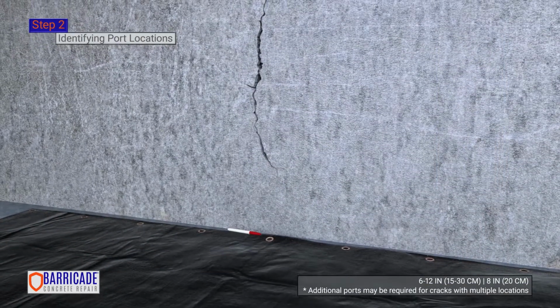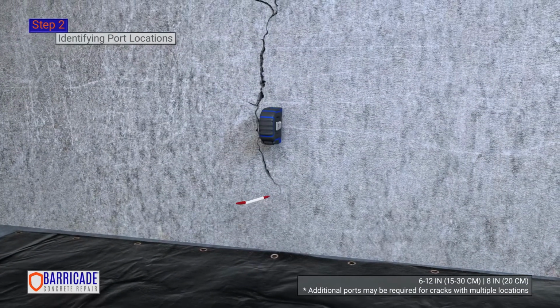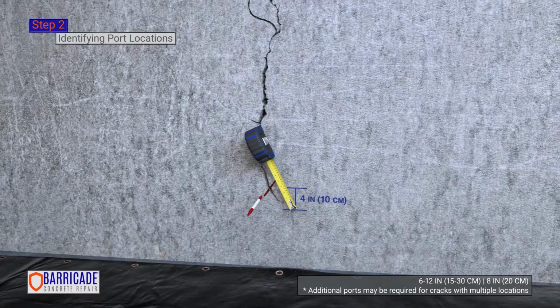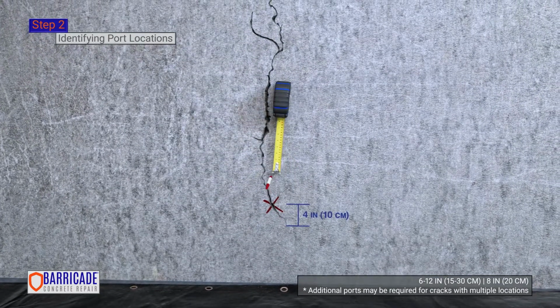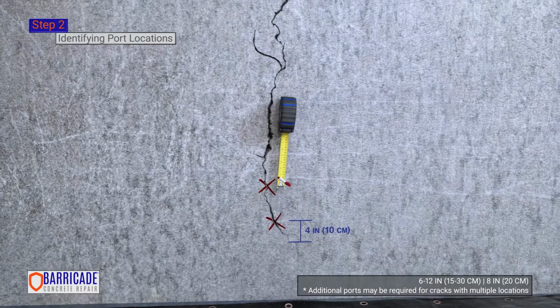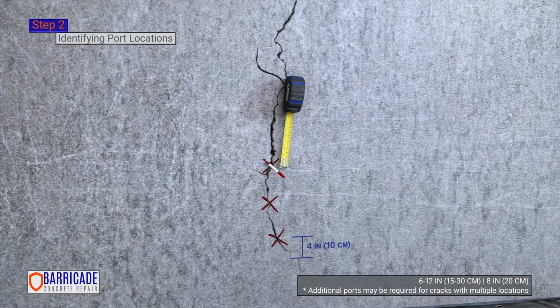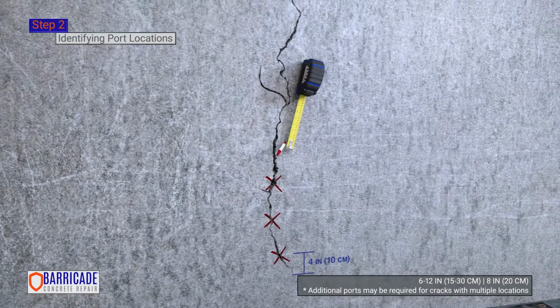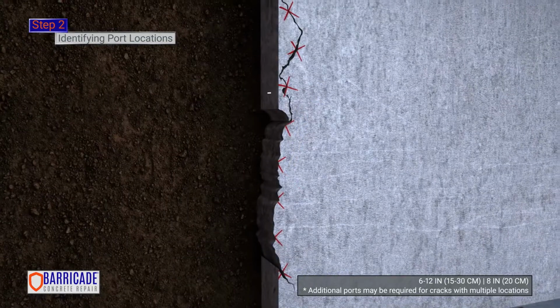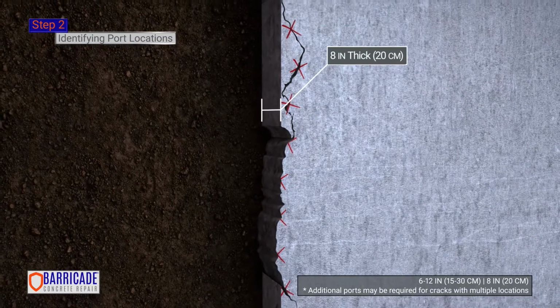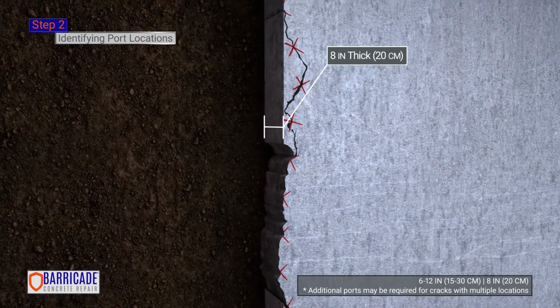Step 2. Port locations. Mark port locations approximately every 6 to 12 inches, starting 4 inches from the bottom of the crack. The tighter the crack, the closer the port should be. For a typical 8-inch thick concrete wall, ports should be installed every 8 inches and no closer than 6 inches. Thinner slabs may allow for 12 inches.